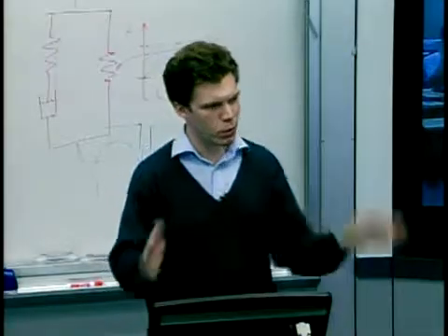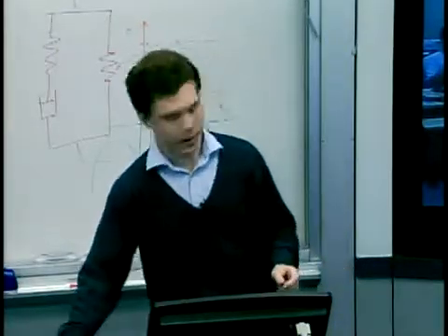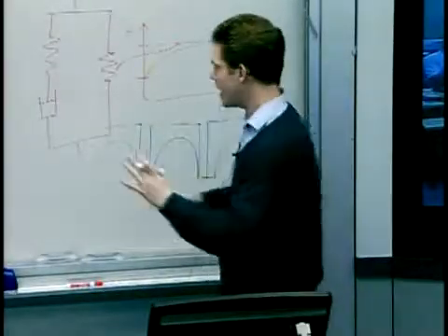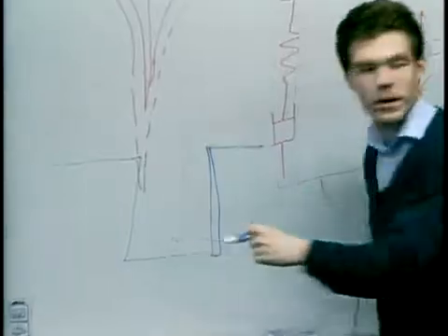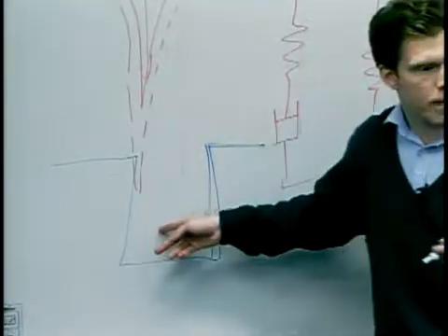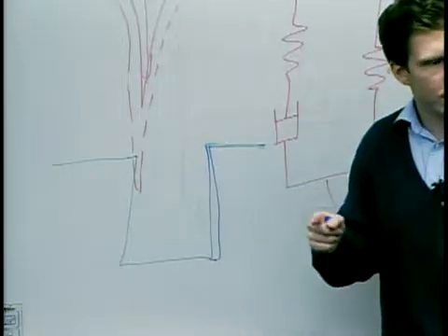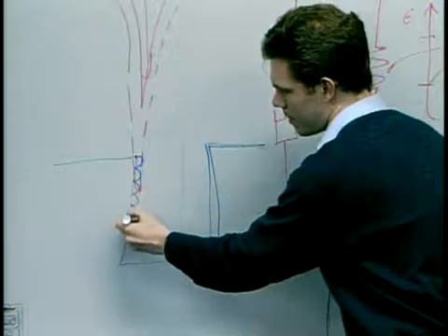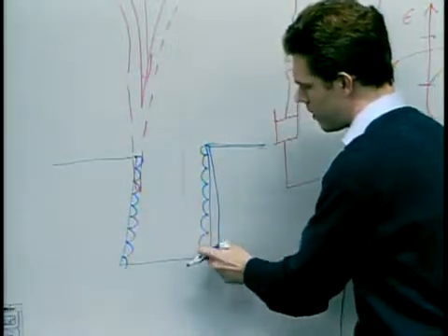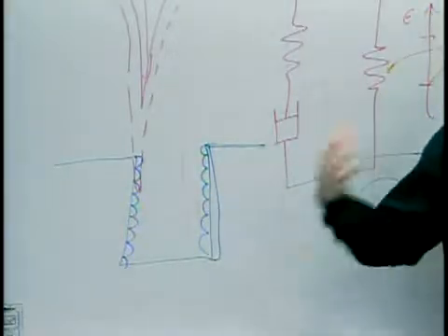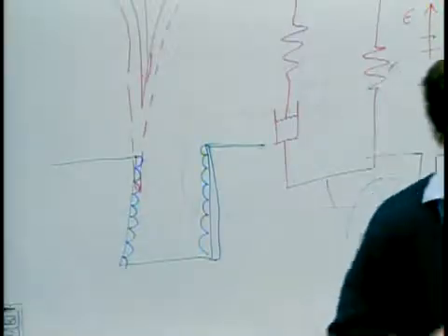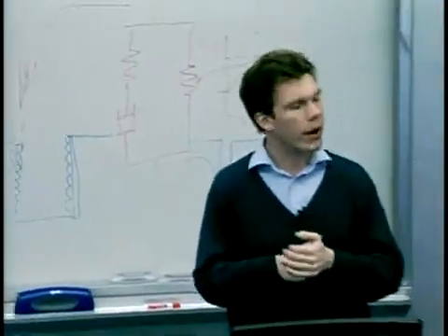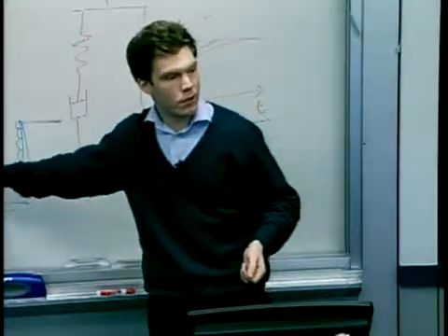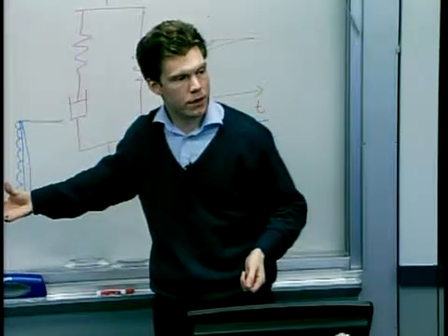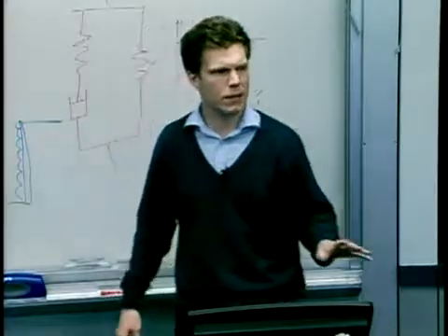However, the problem isn't all to do with friction. Sometimes either your stamp is imperfectly made and there's a negative draft. I mean, I exaggerate, but if that were the stamp and that were the polymer, that's a problem that people run into quite a lot. And if the stamp has been made by deep reactive ion etching, where there's this cyclic etching process and there are these little submicron scallops, you're susceptible to mechanical locking, and there's plastic deformation of the polymer as you pull it off. So it's a good point, yes. And actually, one thing that does work quite well is to leave the Teflon polymeric coating on the silicon after etching, and that does do quite a lot. It has a very limited lifetime, though.